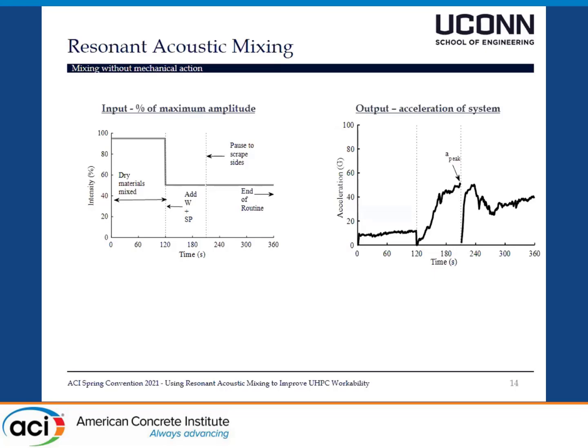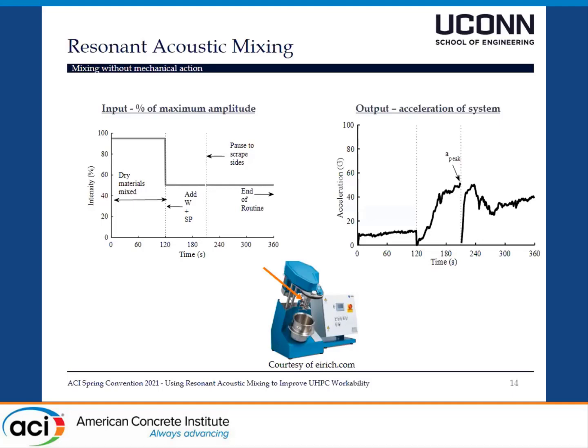And this is very similar to an intensive Eirich mixer. What's different is that you're getting the measurement of the entire mixing container, as opposed to just the torque measurement of the impeller tool. And by getting the torque measurement from the impeller tool, you're really only monitoring the amount of material that's closest to the impeller. So the power that the material feels the farther away you are from the impeller could be different than the amount of power the material near the impeller feels. At least with this acoustic mixer, you're getting the entire mix acceleration.